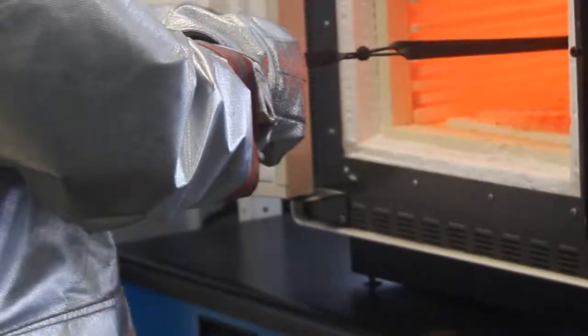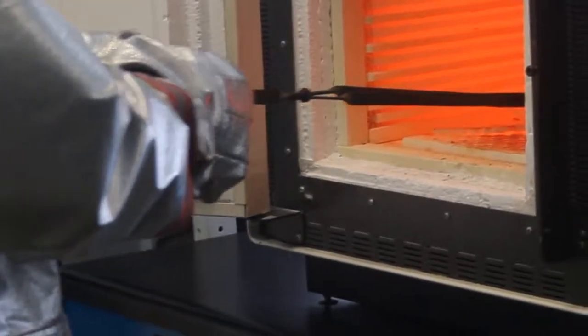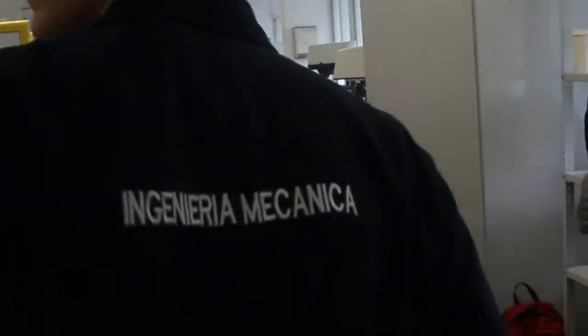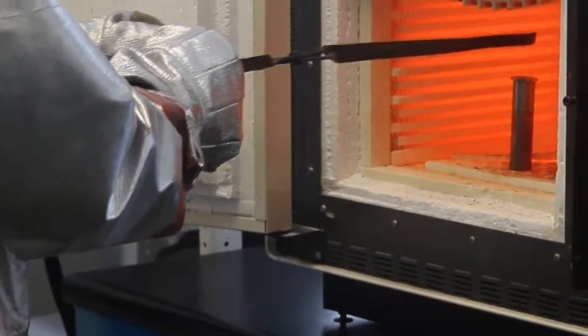After putting our material into the oven, we made sure that it was there for a long period of time, approximately 1 hour. So the complete part of our material was 100% austenite, because it was at a higher point than the austenitic line in the diagram. So for this reason, we took the material out of the oven. We put it in a special machine where you do the Jominy test. What it basically does is grab your piece of metal and squirt some water into the bottom part, so you have a faster quenching rate at the bottom, and it decreases as it goes up. What this does is that at the bottom part of your material you get martensite, then as you go up you have bainite, and then you have perlite.